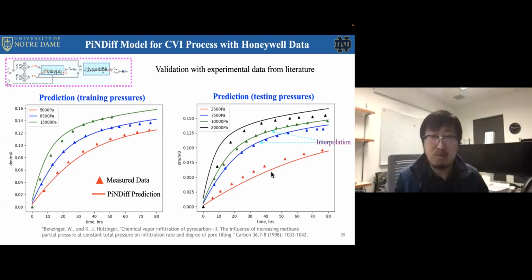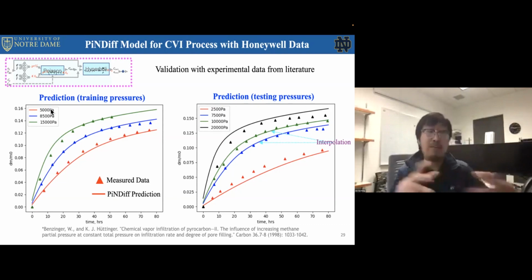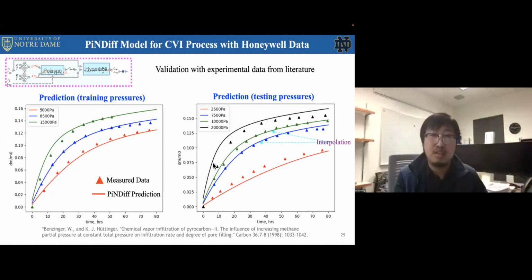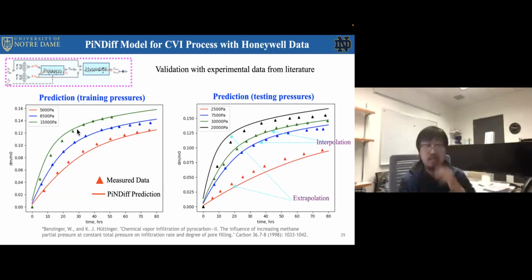So for this red one and this black one, the partial pressure is even out of your training range, much lower or much higher than your training range. The model still gave you pretty reasonable predictions. Remember, we only have those very sparse training data. So those are more like extrapolation. So it has very good generalizability. And this time is with real experiment data.